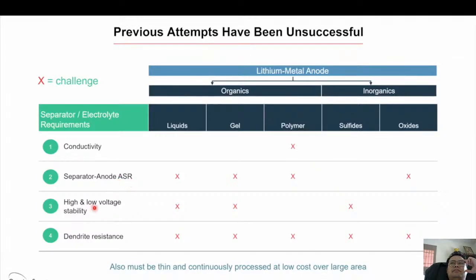The separator is going to be in contact with the anode and cathode over the life of the cell, and also in contact with both the 0 volts relative to lithium on the anode side and the high voltage of the cathode side. So maintaining stability over that very wide range of activity of lithium. It's about 80 orders of magnitude of lithium activity when you go from 0 to 4 volts. 80 orders of magnitude is such a large number. It's literally an astronomical number. There's something like 10 to the 80 atoms in the universe.